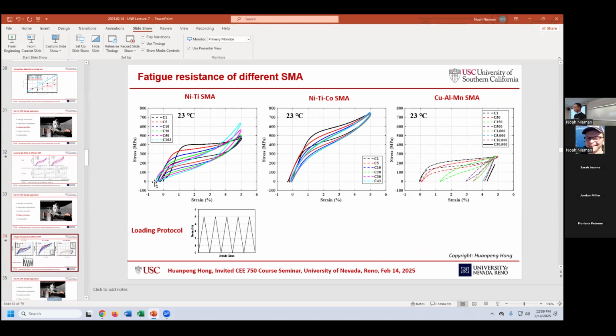The reason for this is that for the nickel titanium alloy, when manufacturing these materials, there will be a lot of extrusion or rolling or cold working on it. It will leave a lot of residual phases in it. So that means before we start this test, this material has been deformed in some way, with some kind of residual phases in it. So that's why when we load it to some point and then unload it, we somewhat trigger the residual phases in the material.